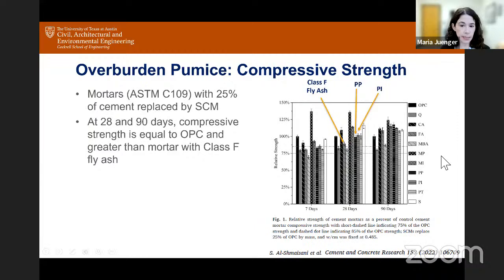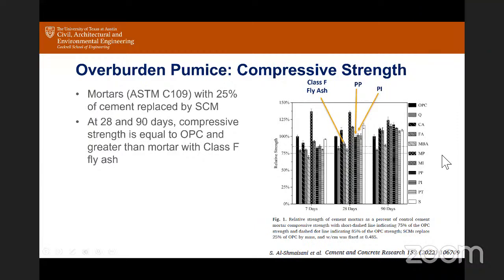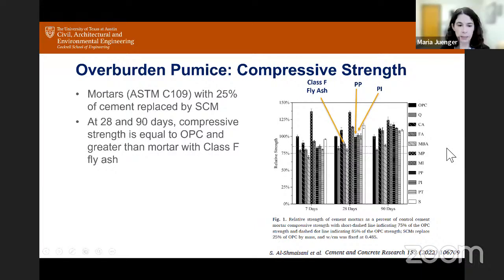Another thing we like to look at is compressive strength. These are compressive strengths of mortars according to ASTM C109, and we took 25% of the cement replaced with the SCM. And what you can see here, the black columns are the Portland cement, and the reference is relative strength as 100% of the Portland cement at that particular age. The dotted lines are an 85% line and a 75% line, just to get a sense of what you would expect these types of materials to do.